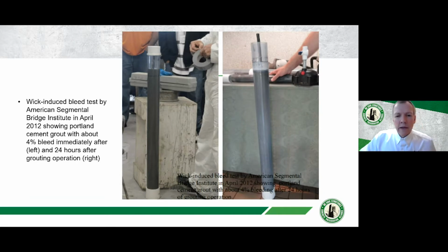So there are many reasons why you can end up with issues that result in corrosion, but I'm going to just touch on the two most common ones. The most common, in my experience, is the presence of voids. If you have a void in your grout, then you have a location where the steel may not be protected. You have a location where water can collect, and even worse, salt water can collect, and you can have severe damage and corrosion in the areas where you have voids.